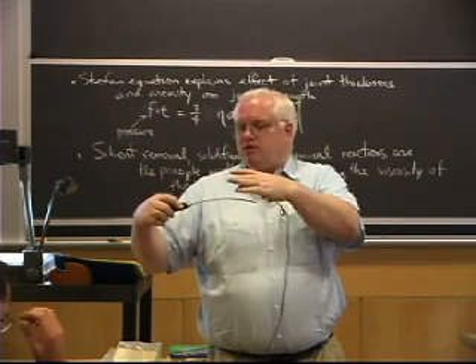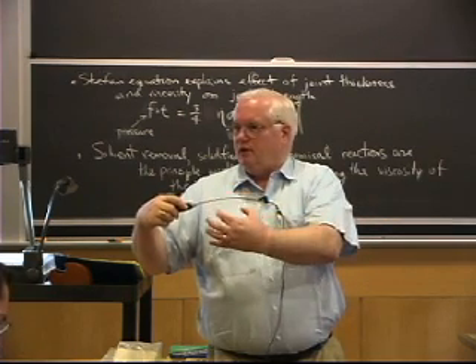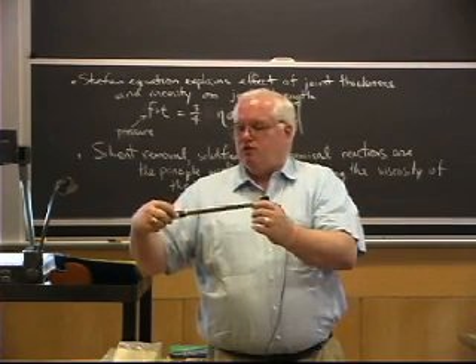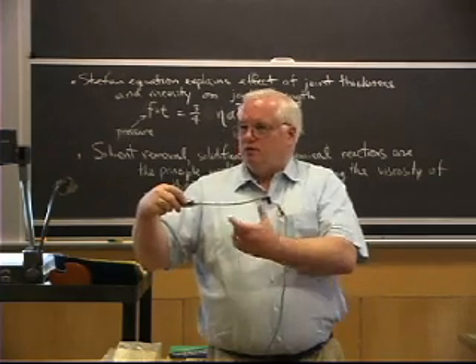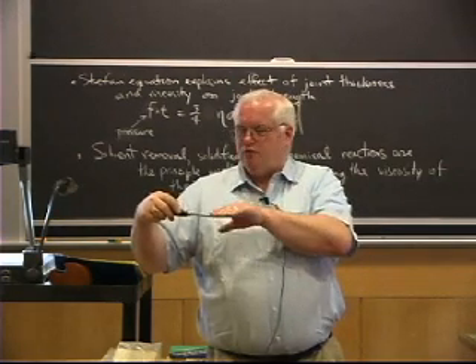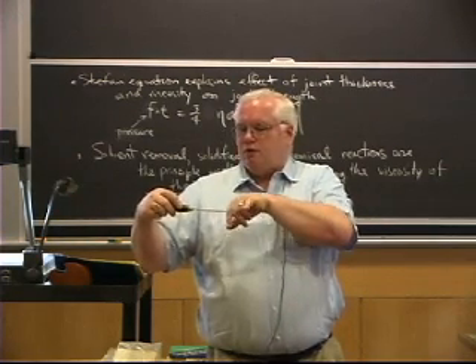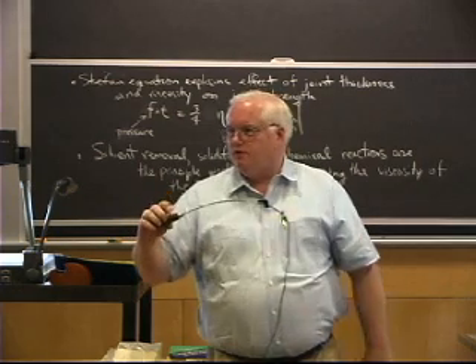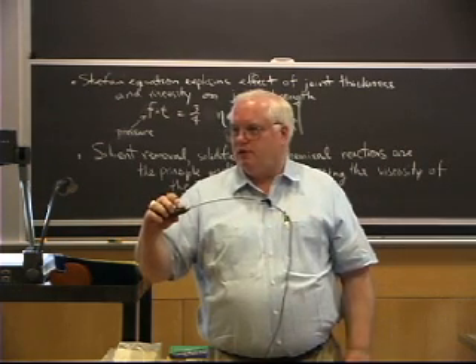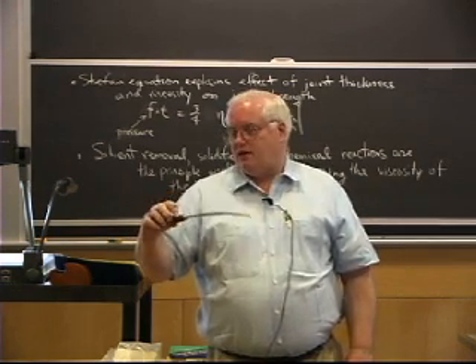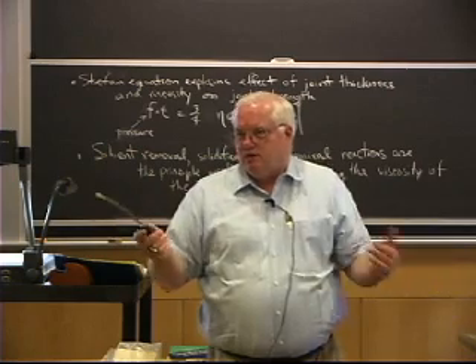And if it yields and shrinks a little bit, when the whole thing cools and everything becomes uniform temperature again, that material will have a curvature to it, the opposite of the direction that it was when you heated it. In fact, that's how you get residual stresses in thick plates.